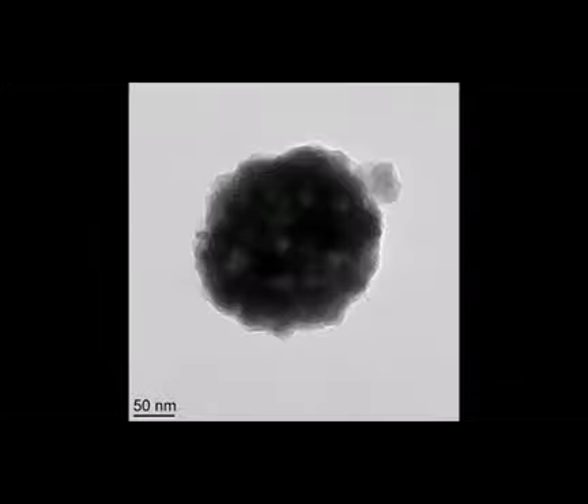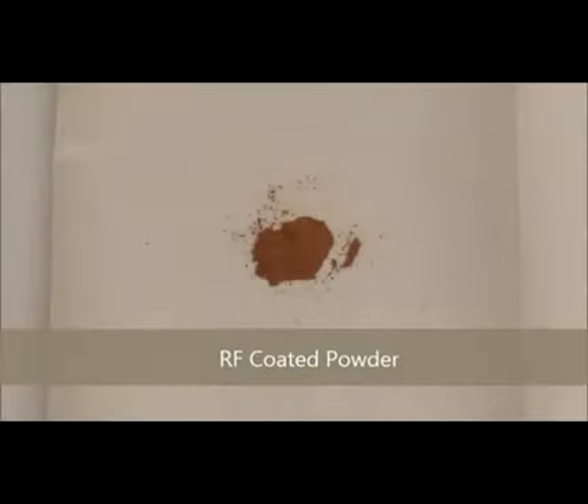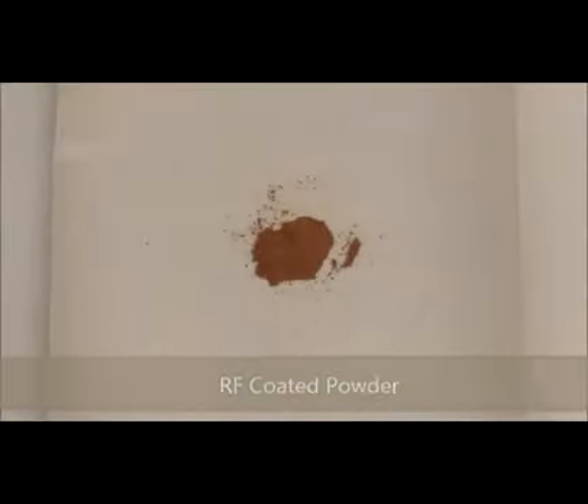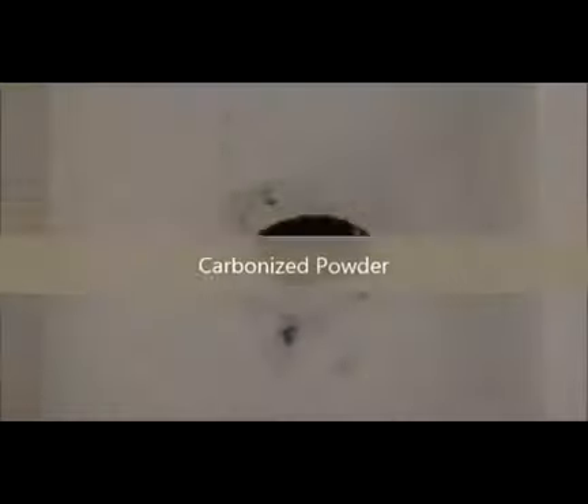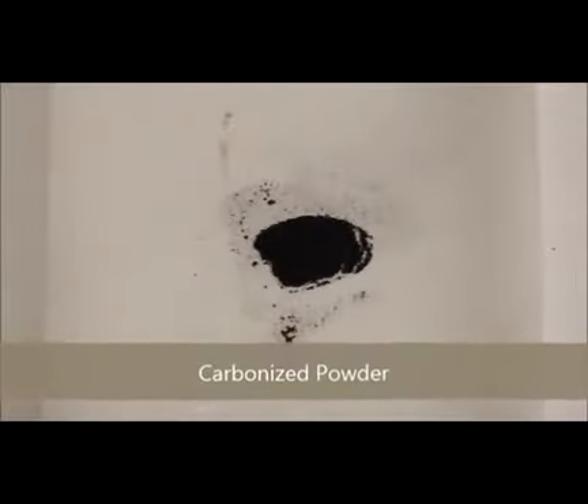Here we have a magnification of a particle, and we are able to see a thin layer of the RF coating. Here we have an image of the RF coated powder. Here's an image of the carbonized powder. After calcination with argon gas, we can see how the RF coated powder becomes carbonized.